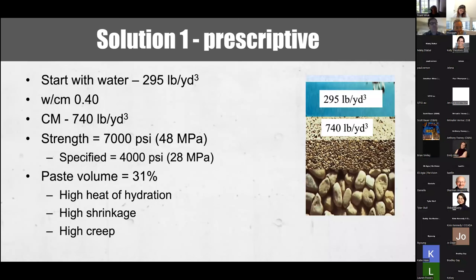This mixture also has a high paste content, which will cause associated problems such as high heat of hydration, shrinkage, and creep. The mix will not be the most economical one because of the high cementitious material content.